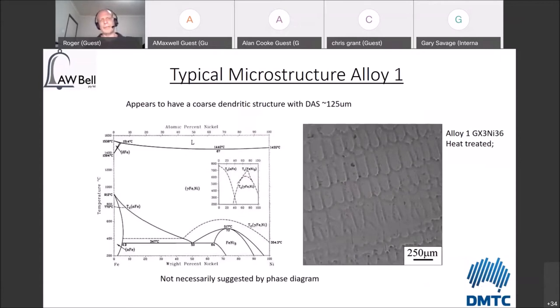Now, this is a very interesting thing because, of course, there's a lot that's been written about the mushy zone inside materials and the contribution of mushy zones to tearing. This is a little bit different because we can look at this without that two-phase region. We can say, okay, it starts solidifying and we're only driven by temperature rather than phase. So the outside solidifies first, you have this onion skin effect, much the same way as aluminium bronze does. And then it moves forward to the inside.